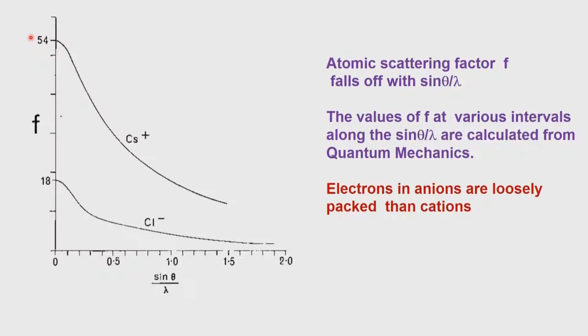So, what it also tells us is that we can represent also ionized atom positions with respect to the scattering behavior. So, whether it is in the neutral position or in an ionized position, depending upon the level of ionization, we can actually have the value of f diffract. So, for chlorine the curve will start from 18 at 0 value and then fall off exactly like whatever is shown here.